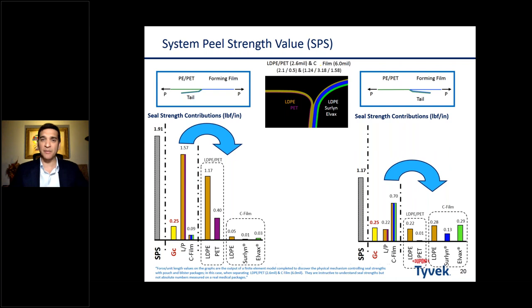So let me explain what's going on. If I am pulling back towards the film side, what happens is that at that edge, the polyethylene is deforming. It's either elastic or inelastic. It's either stretching and permanently deforming, or it's absorbing and maybe comes back a little bit. But either of those two things is what's occurring. And that resistance is what's giving me a very high seal strength value.